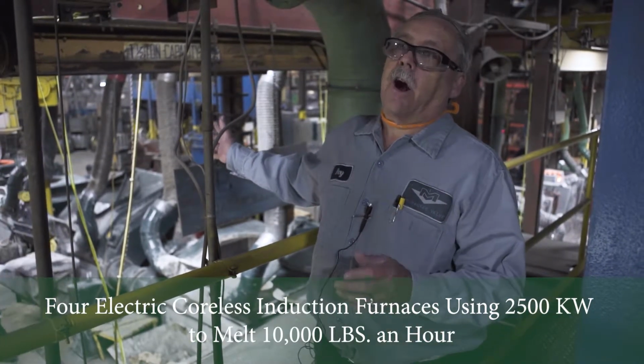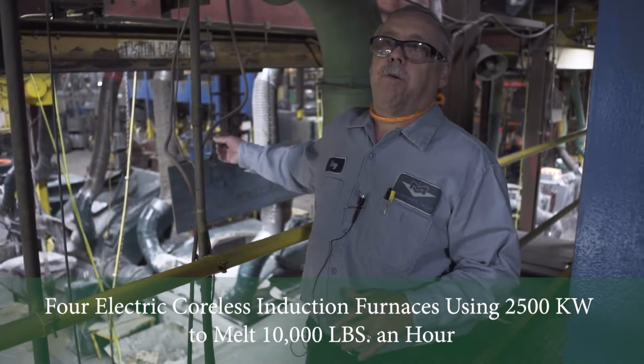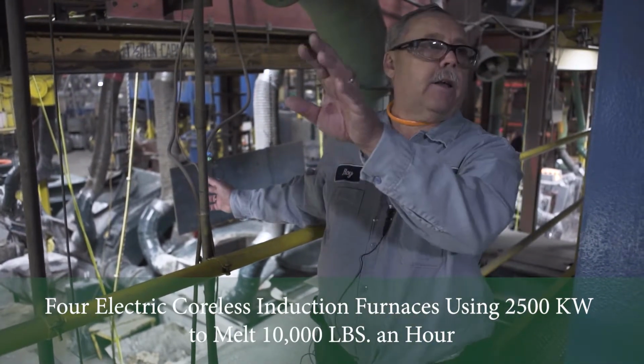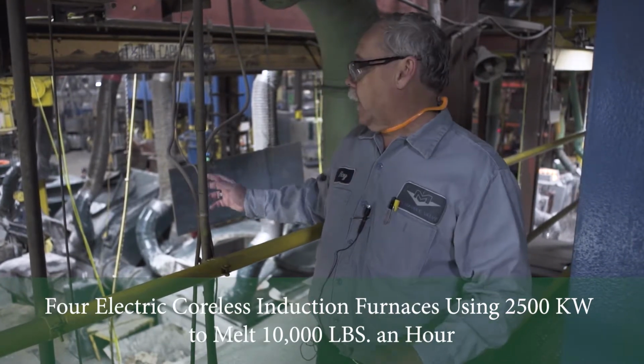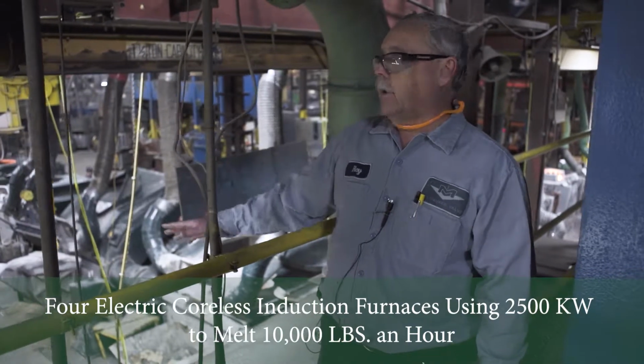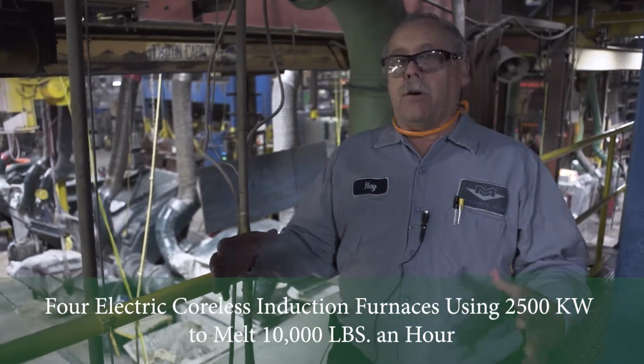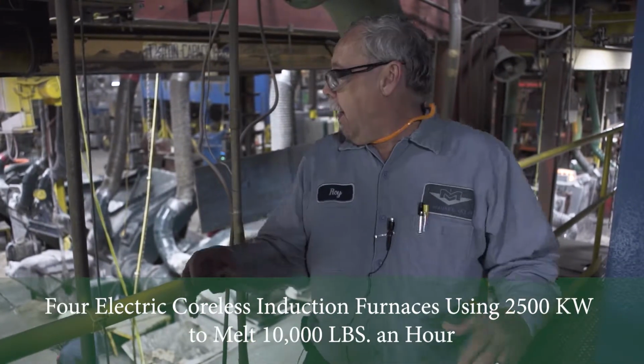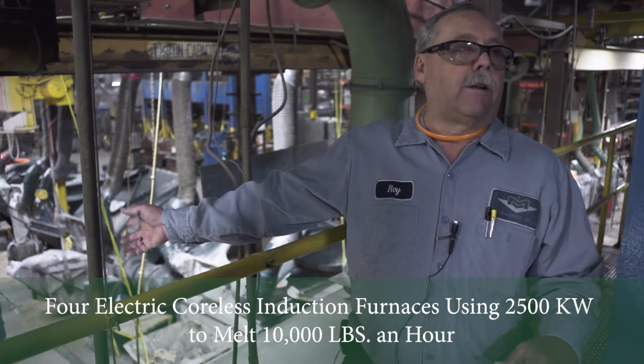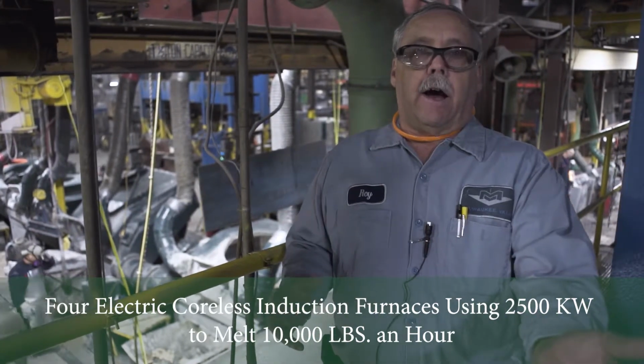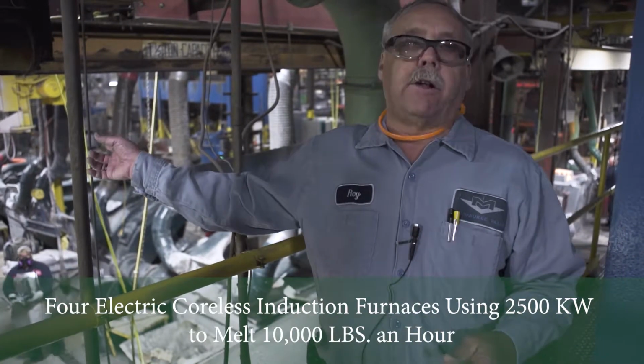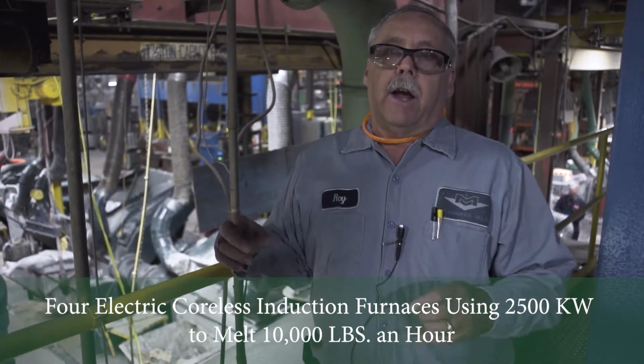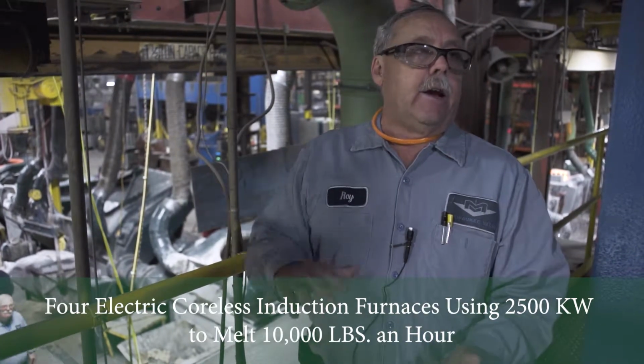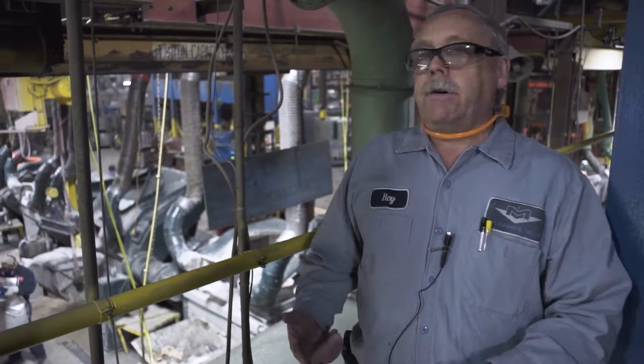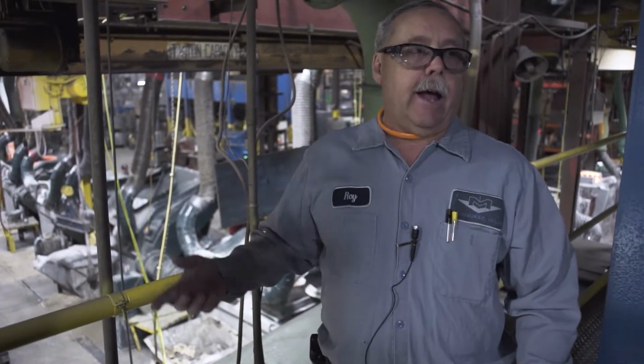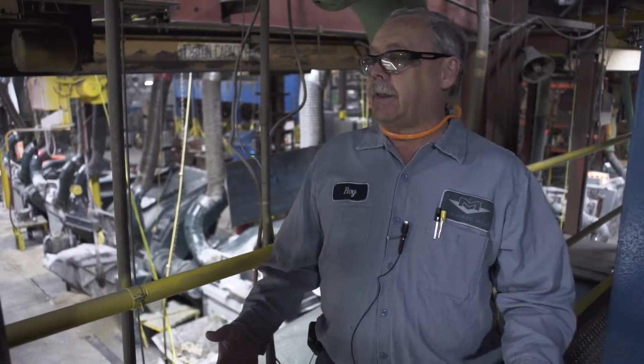Again, like I talked about earlier, we pull a plug before we pour any metal, and then when the metal is good, the lab will let them know that it's good. And they'll transfer the metal to our pouring device, which has a stopper rod, and it holds about 1,500 pounds of metal. The operator looking in is monitoring that. The data, how much the pour time is supposed to be, is automatically transferred to it, and he knows what casting is there, and he matches the pour time with the opening of the orifice to get the desired pour time. We record the pour time, and we record the temperature as each mold is poured. So we have to keep that data also.